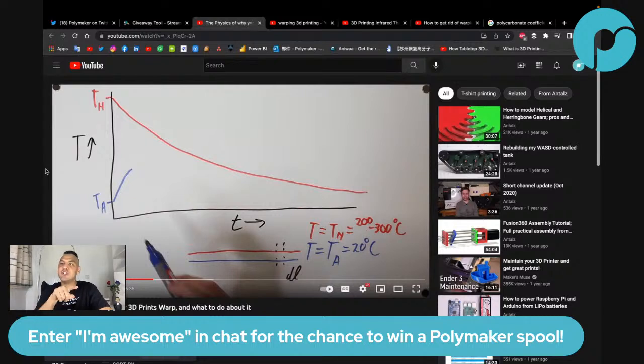The blue one is the temperature of the layer below, and as the layer above is coming with the heat from the nozzle, it's going to transfer a little bit of heat to the second layer. So that's why you can see the temperature from the layer below in blue is increasing.